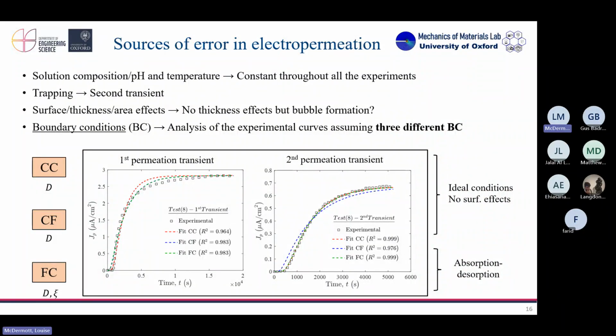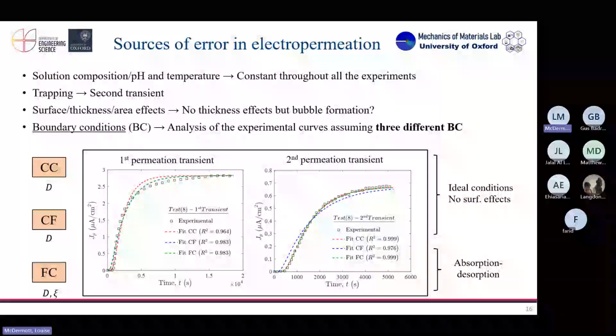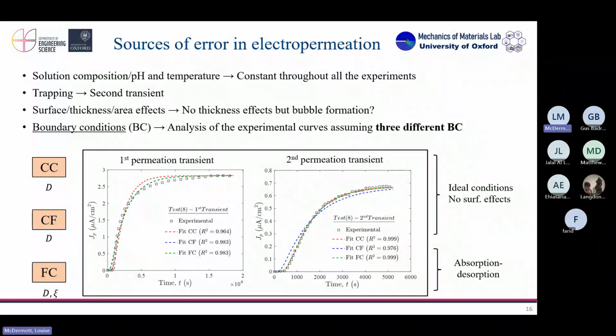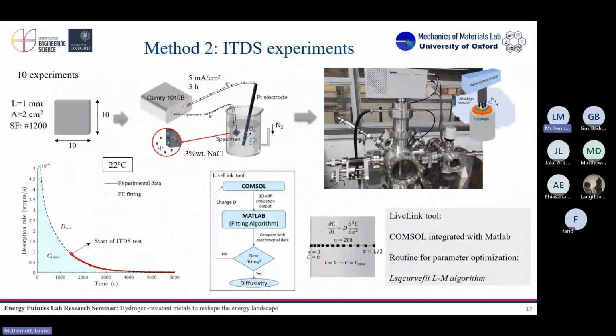So you really, it's a bit arbitrary. You say, okay, I will consider this, and I will provide a diffusivity based on just my decision. And then the second method, which is of course the one I'm supporting, is based on thermal desorption. Basically, you charge your sample with hydrogen, but you don't measure any diffusivity there. You just fill it with hydrogen.